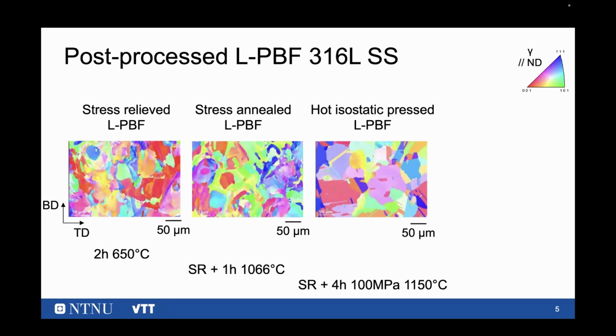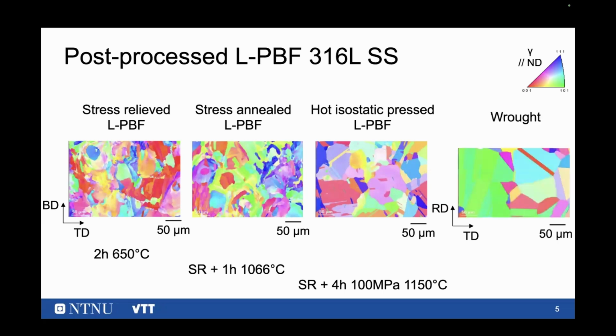If we increase the post-treatment, first only stress relief, we still see the microstructure that is present after additive manufacturing. The grains start to rearrange when we also apply an annealing treatment at higher temperature. And we see that the grains are almost fully rearranged to an equiaxed structure with some twins present as well after the hot isostatic pressing at high temperature as well as high pressure. It's worth noting that this structure is actually quite similar to the conventionally rolled structure, also rather equiaxed grains and also some twins that are present.